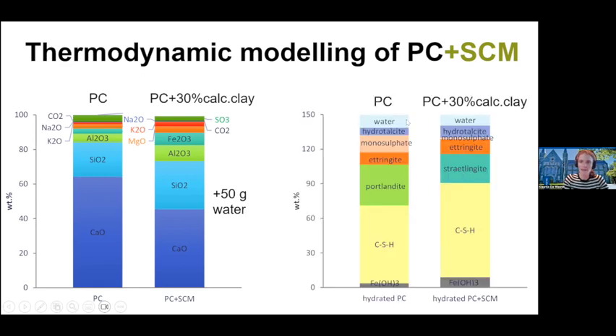And what I get then is here on the left, it's still the phase assemblage I earlier showed for Portland cement. And here you see what happens when we replace 30% of our Portland cement with a calcined clay. I just picked a random calcined clay from one of our research projects. What you can see is that this calcined clay, when it reacts, consumes all Portlandite in the pozzolanic reaction. And what it does, it forms more CSH, and it typically also forms or can form more AFM. And in this case, as we ran out of all Portlandite, we even formed stratlingite. So you can see that the pozzolan or the SCM is greatly affecting your phase assemblage.